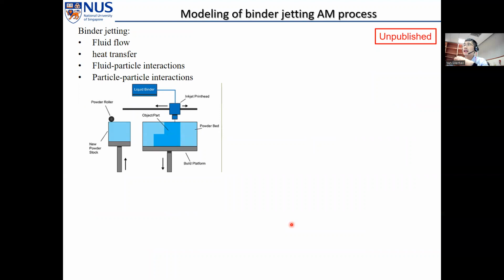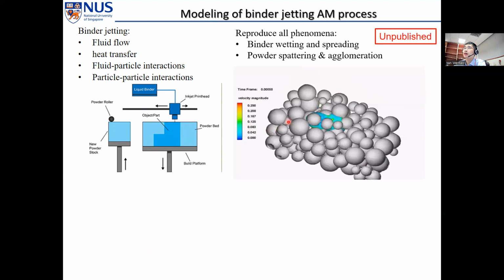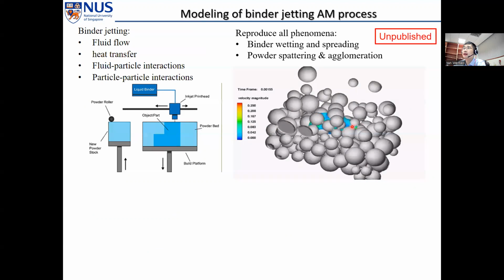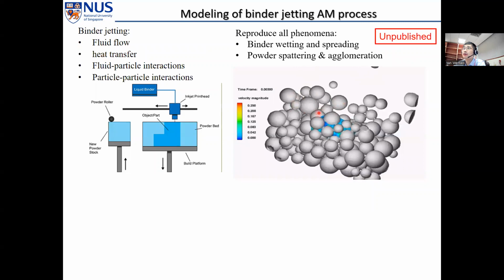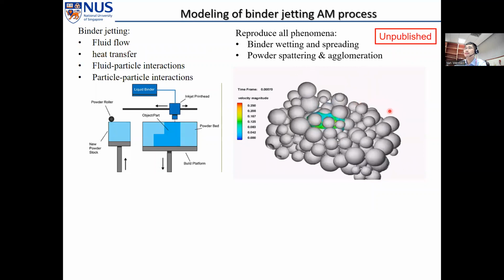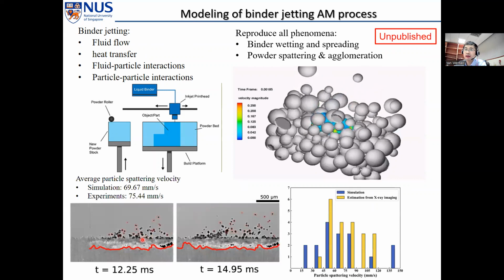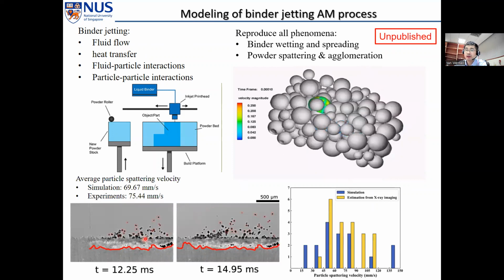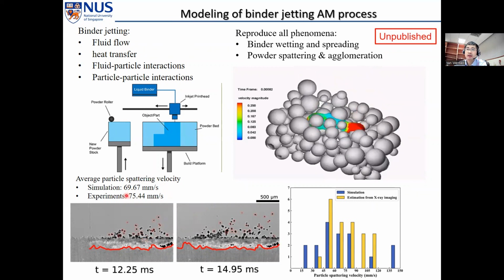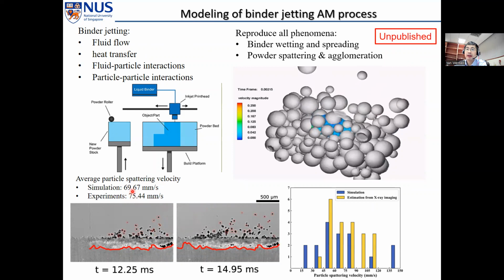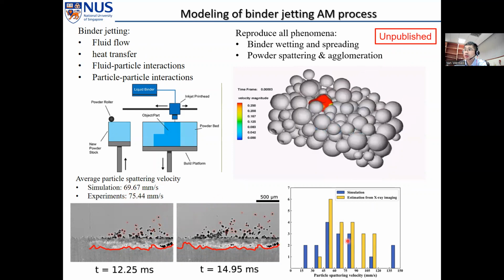Another very popular AM process is binder jetting. It's even more complex, including fluid flow, heat transfer, fluid-particle interactions, and particle-particle interactions. So we can reproduce all the phenomena like binder wetting and spreading, as well as powder spattering and agglomeration. This is validation against the high-speed X-ray imaging at Argonne National Lab. The average particle spattering velocity is pretty close, and the spattering velocity distribution is also similar.